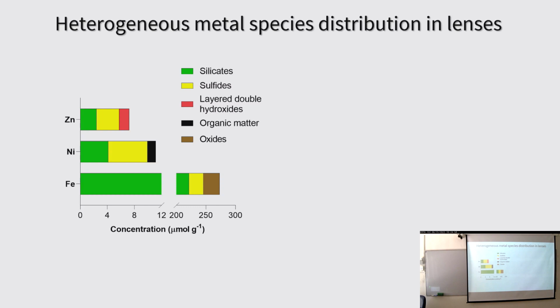And you can see here we have some common pools of these metals. So we have the silicates in green and the sulfides in yellow. But there was a distinct difference in the third phase. So for iron, we have a specific pool of iron oxides, likely present due to redox oscillations that are taking place within the lenses. For nickel, we had a more significant contribution of organic matter interactions, whereas for zinc, more layered double hydroxides. Now, both zinc and nickel are prone to form layered double hydroxides, but strong nickel organic matter interactions are also known to hinder the formation of nickel layered double hydroxides.